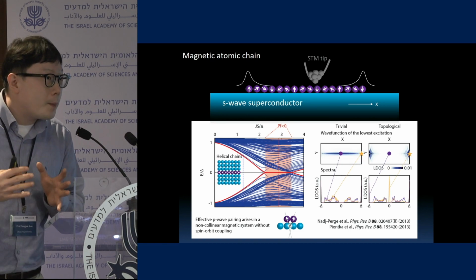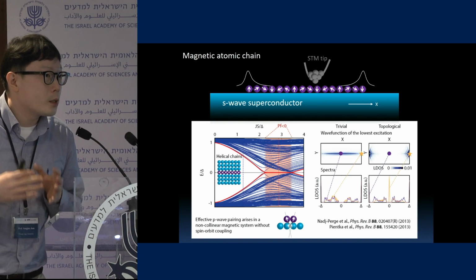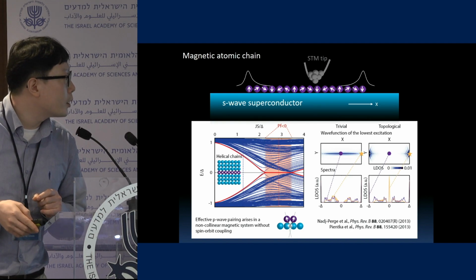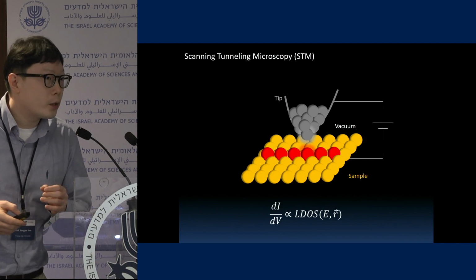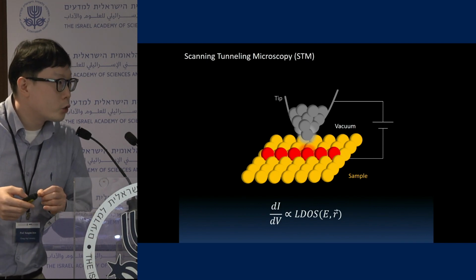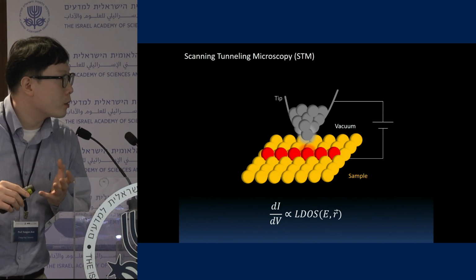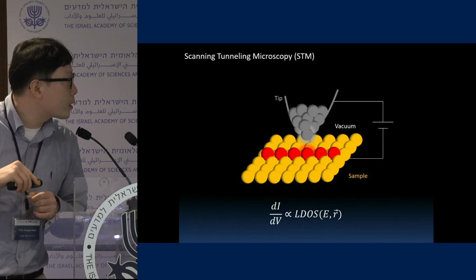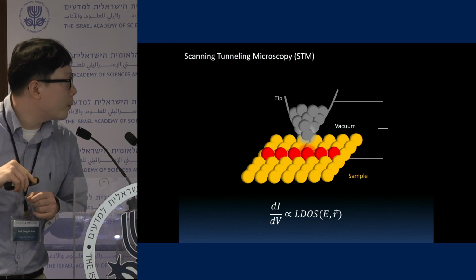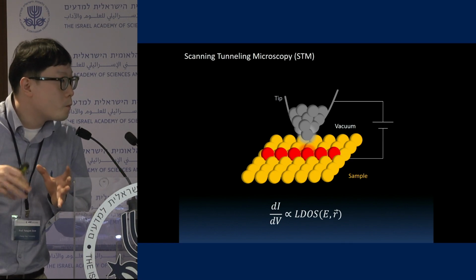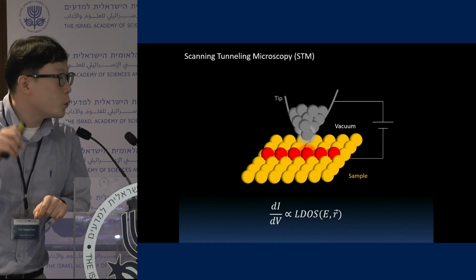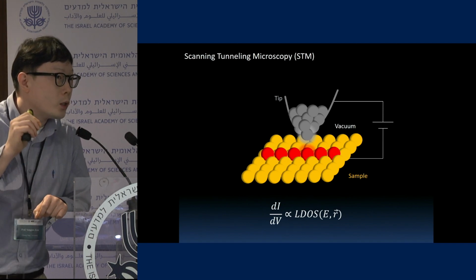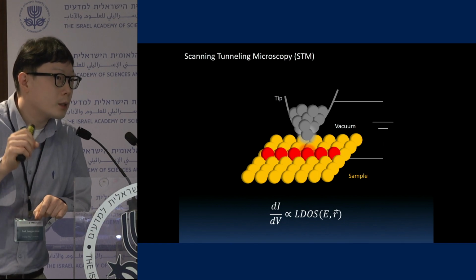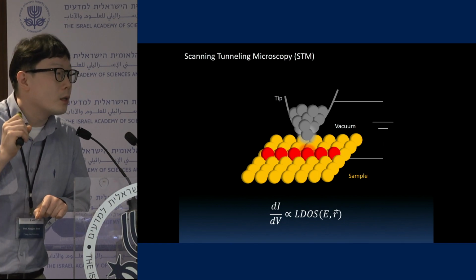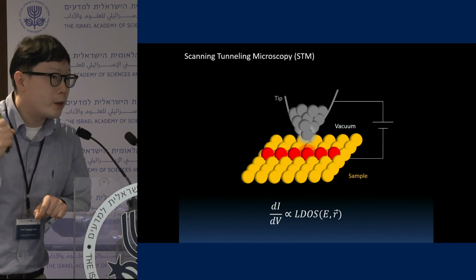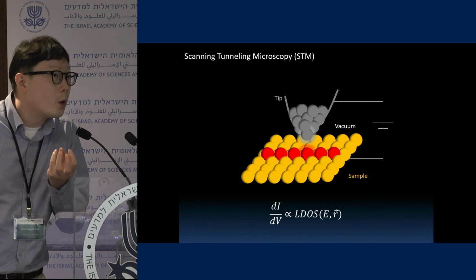And then, keeping in mind all these theoretical proposals and our understanding, we chose a material with a lead substrate and iron chains, and then we measured with the scanning tunneling microscope. Scanning tunneling microscopy basically measures the tunneling current between tip and sample, and by moving the tip position on the surface, we know where we are measuring, we know the structure, and at the same time we measure the density of states, which gives us electronic properties of the sample. So it is a very powerful way to measure this kind of localized states.